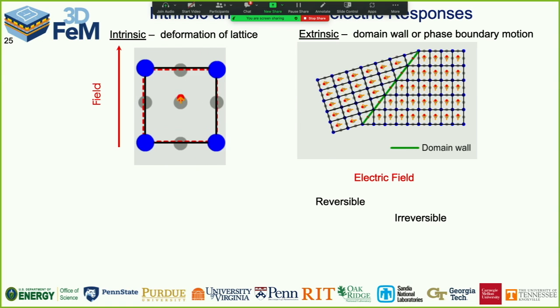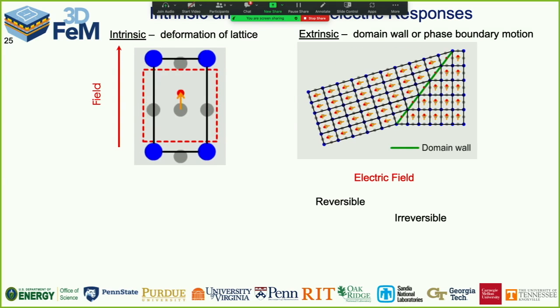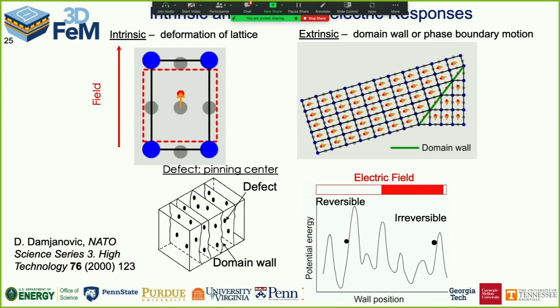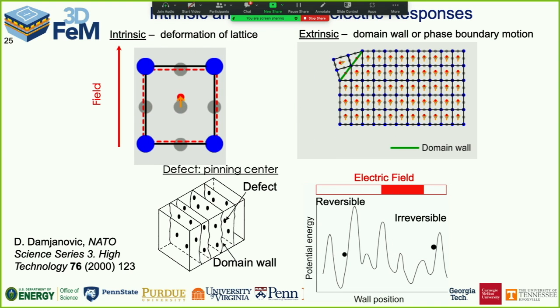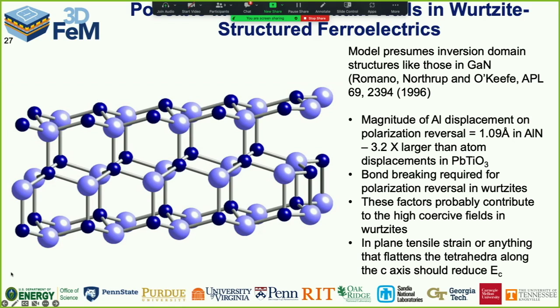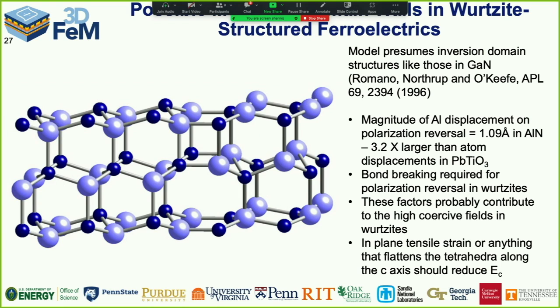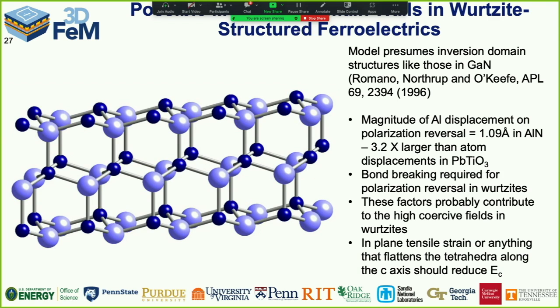So how would we prove this? We use the same sorts of basic fundamentals that I talked about on Tuesday. Recognize that I have intrinsic responses, I have extrinsic responses due to the motion of domain walls, and anytime I move a domain wall around, there will be a hysteretic component to it. Let's go find that at subswitching fields by doing Rayleigh analysis. And so we speculated that the way these materials would switch is via basically an inversion of the puckering of the puckered hexagonal ring in the Wurtzite crystal structure.